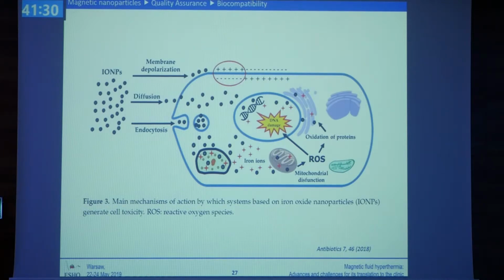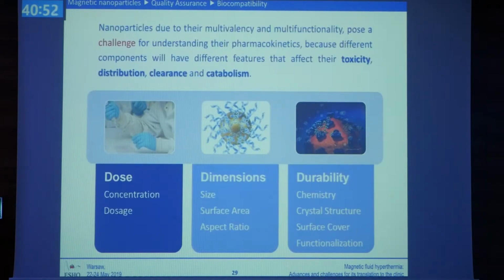Because iron oxide nanoparticles interact with the cells through endocytosis, diffusion, or perhaps even through depolarization of the membrane. And sometimes when we have a lot of ions inside the cytoplasm, we might get disturbance in the functioning of the mitochondria or the Golgi system or anything else inside the cell because of the reactive oxygen species that is known to be produced because of these iron ions. So we know that up to a concentration or a dosage, the iron nanoparticles do interact with the cells, but without being toxic. Above some dose, they can be very toxic, and we can see that in the viability of